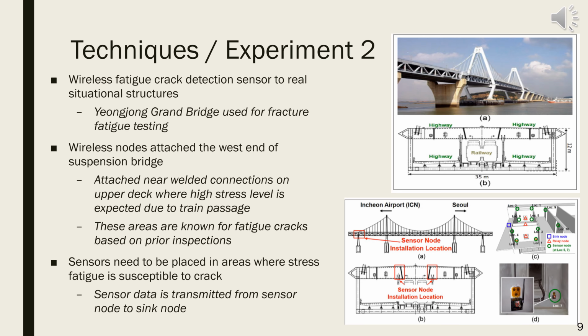This is experiment number 2. The application of the wireless fatigue crack detection sensor to real structures is shown here. The Yeongjong Grand Bridge is used for fatigue crack testing. The wireless stick and detect nodes were attached to the west end of the suspension bridge. They are attached near the welded connections on the upper deck where high stress levels are expected due to train passages. These areas are known for fatigue cracks based on prior inspections. These sensors need to be placed in areas where fatigue cracks are susceptible to form. The sensor data is then transmitted from the sensor node to the sink node.